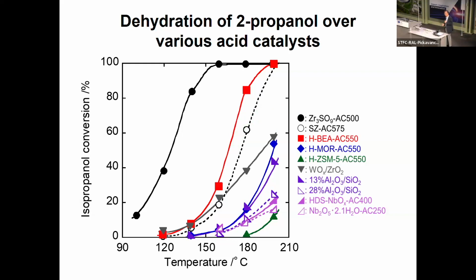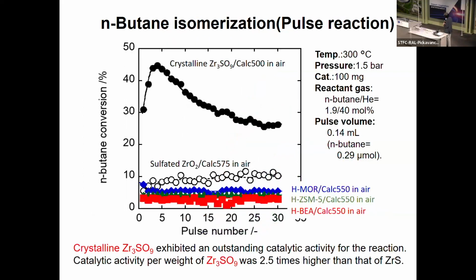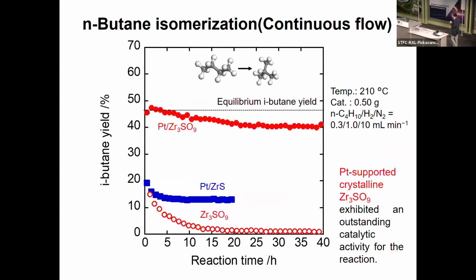That kind of thing has to be done more in any case. This catalyst is also good for n-butane isomerization, as you can see, but it shows some deactivation over time, though the activity is much superior to the conventional one. You can put platinum onto it, and then you can get stabilization. In this case, we have to feed hydrogen at the same time. The hydrogen can support some active state, because the hydrogen can be activated on the platinum. The activated hydrogen can migrate to some places on the surface. These kinds of things happen. Therefore, the catalyst becomes very stable.